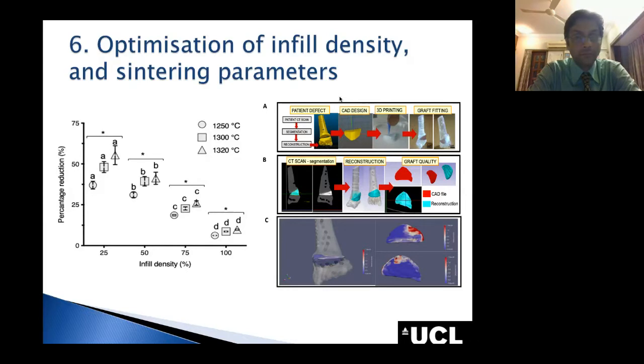To validate that, we used the case study of radius malunion. As you can see here, on the top, in part A, we have a plastic replica, and we inserted a hydroxyapatite printed scaffold graft inside, and that graft was scaled up depending on the percentage reduction of the sintering temperature used. To validate that this equation and this factor were correct, we took a CT scan of the 3D printed plastic replica, and you can see in the C image, based on the distance mapping, there is a maximum of 1 millimeter of non-contact between the plastic replica and the graft itself, which is clinically satisfactory.